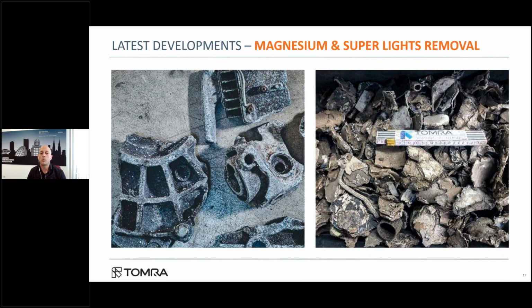Another development is the removal of magnesium and superlights. Depending on their exact process, aluminum smelters can face many potential problems with scrap that contains high magnesium content. For example, there can be an increased pot time leading to higher energy consumption, extra additives needed for chlorination to remove the magnesium, the addition of primary aluminum to dilute, or an increase in magnesium waste products as dross.